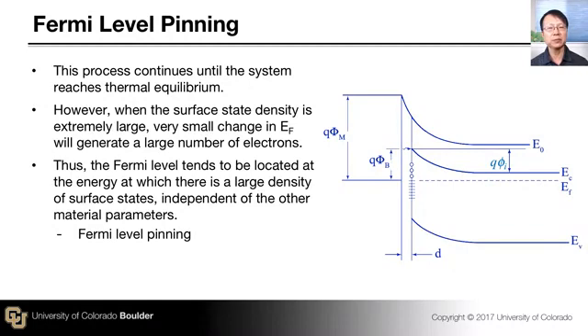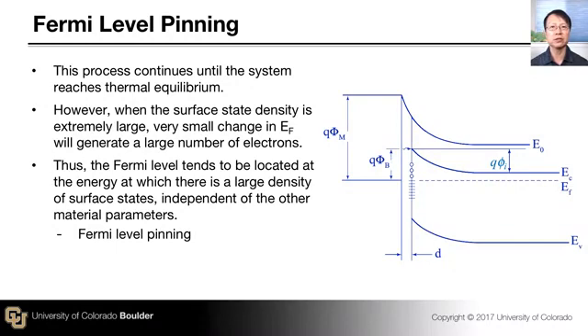This phenomenon is called Fermi level pinning. It doesn't matter how lightly or heavily doped your semiconductor is — your Fermi level will always get stuck at that energy level. Fermi level pinning takes away a very important degree of freedom for engineering semiconductor devices, making it a major source of degradation. Reducing the surface state density has therefore been a major topic in semiconductor device development, to prevent Fermi level pinning and the consequent degradation of device performance.